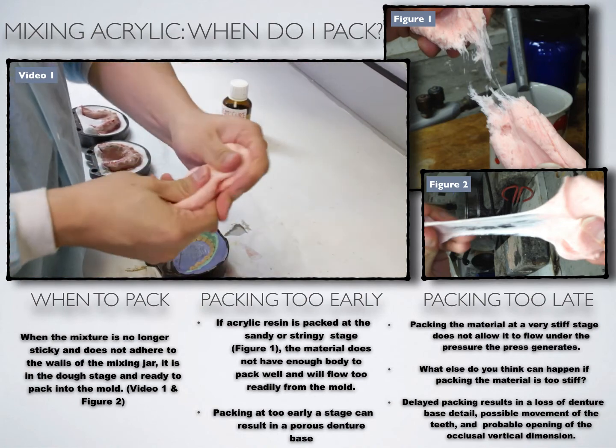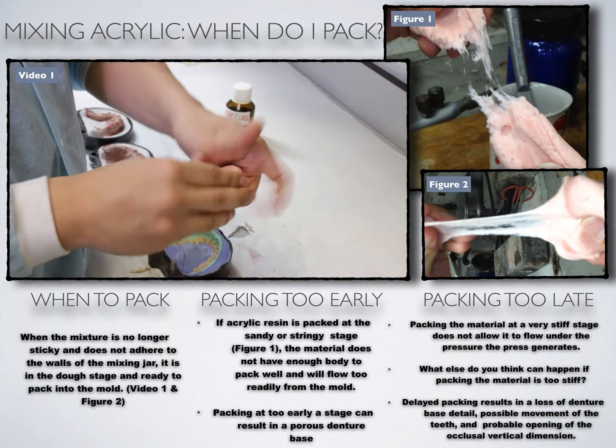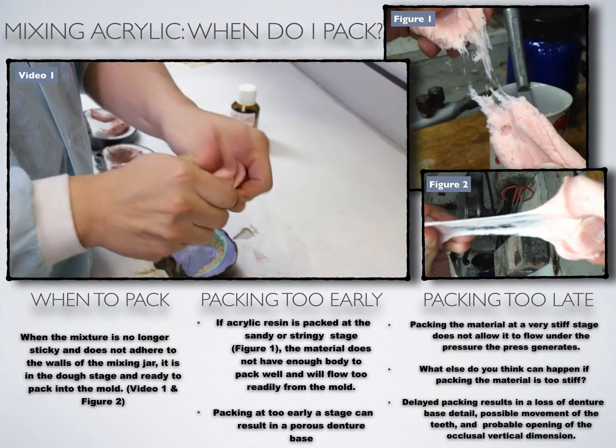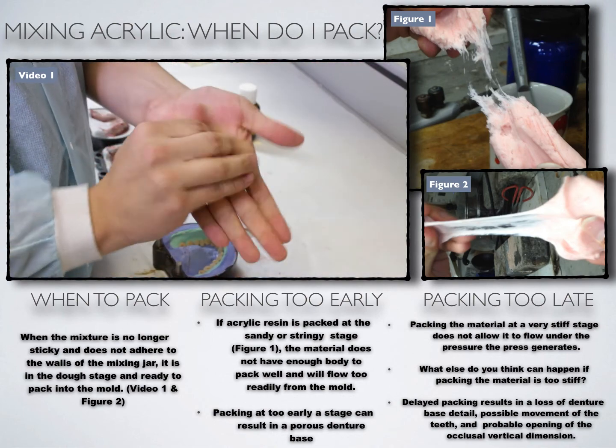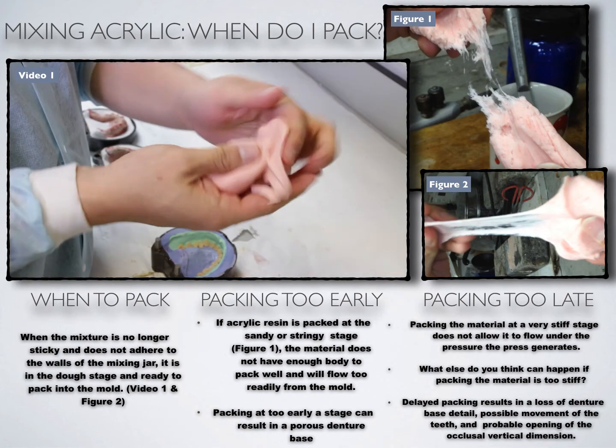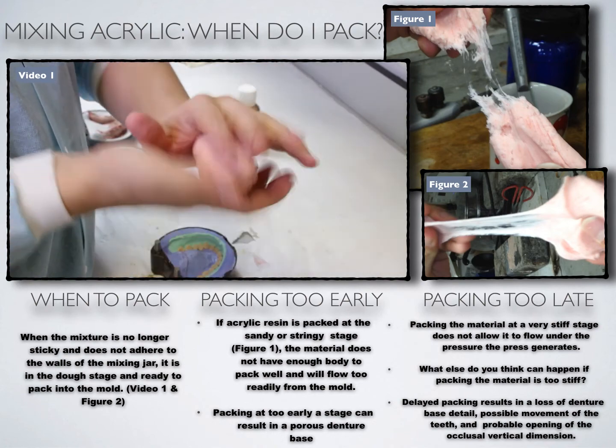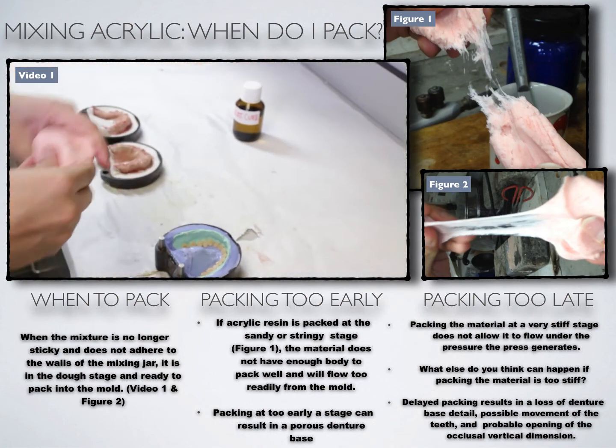If you pack too early, what can happen? If acrylic resin is packed at a sandy or stringy stage, the material does not have enough body to pack well, and it doesn't really fill the mold as well, right? It just kind of slumps. It's not firm enough to hold dimensions. And packing it too early in a stage will cause porosity in the denture.